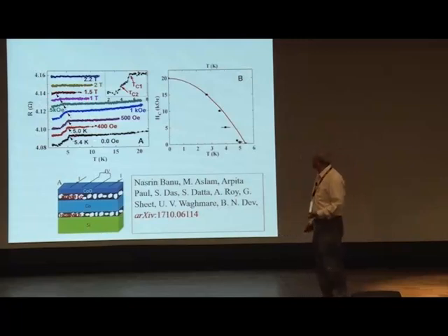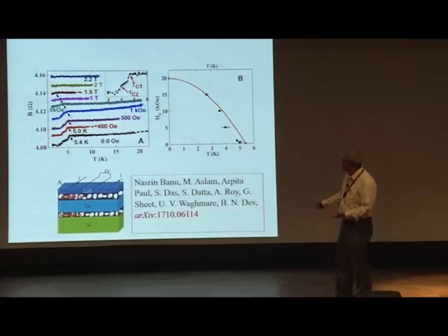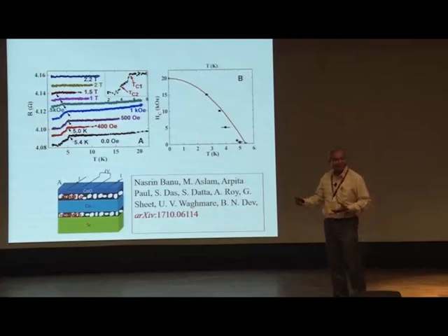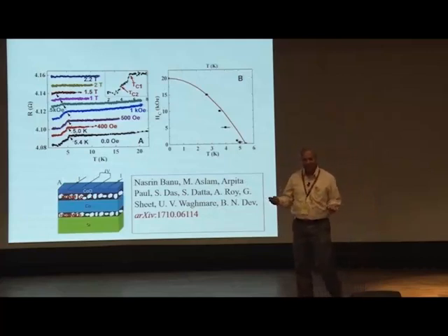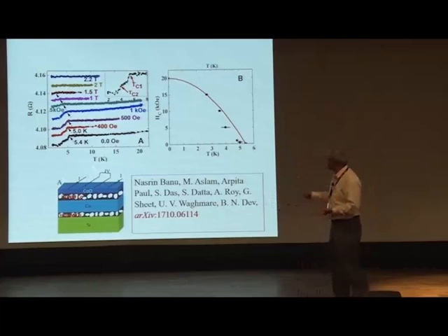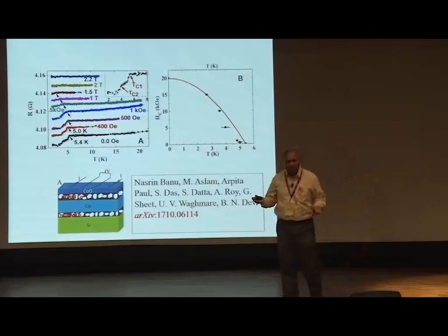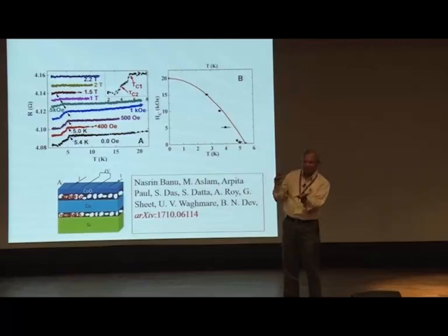But you may ask that this is not going to 0. We can expect that because of the structure, as this cartoon shows: we have high density non-magnetic grains which are superconducting, but in between you have material which is not superconducting, so you have extra resistance sitting there. Now you may ask why this is 5.4 Kelvin here, and earlier it was 9.5 Kelvin. Of course, when you do the contact measurements, there is some pressure that you cannot avoid. So that may be a pressure-induced enhancement of the TC in the other case.